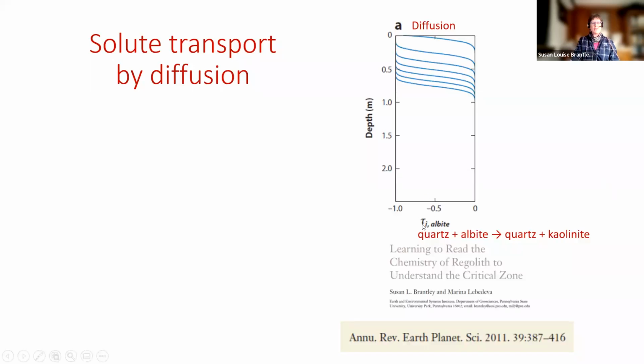So tau, or the mass transfer coefficient, is equal to 0 when you have your parent concentration of albite, and it's equal to -1 when it's 100% depleted. So if you allow rain to fall on a rock that started out over here, where everything was plotted at tau equals 0, so parent composition, albite dissolves away, and you get what's called a reaction front that moves downward with time. So this is a system that's not eroding. This is the albite concentration with time. And what happens is you start out with an incompletely developed front, and then it becomes 100% depleted, and then it moves downward with time.